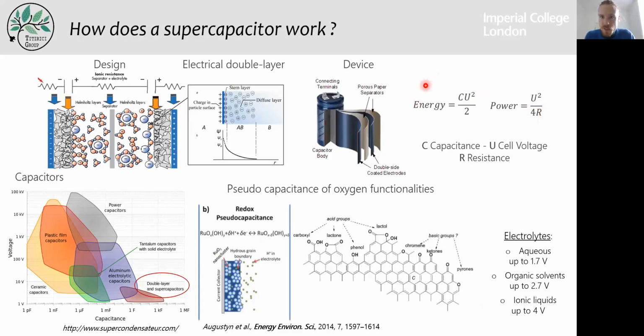And in order to increase the energy density, lots of people have looked into changing electrolytes, basically. So aqueous electrolytes have a thermodynamical or electrochemical window of 1.7 volt. But you can put organic solvents that have much higher, or even ionic liquids that have higher resistance. The problem is that if you change, then you also increase the resistance of your device, and that leads to lower power capabilities.